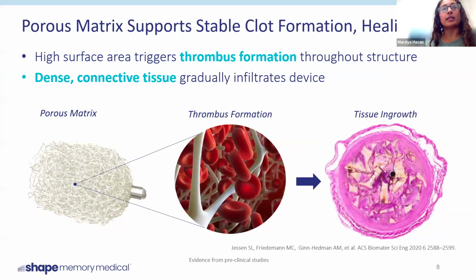The way the embolization aspect of this device works is we have an extremely porous material where blood will make its way through the foam component, and it'll end up stagnating within the pores of the foam. That stagnation triggers the clotting cascade. And that's where we end up seeing the clot that forms to block the blood flow in the rest of the vasculature. Over time, what we have observed is that there is a dense connective tissue that eventually forms around the device. I'll again go more into detail about this.